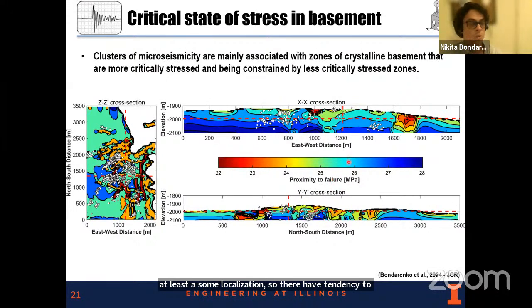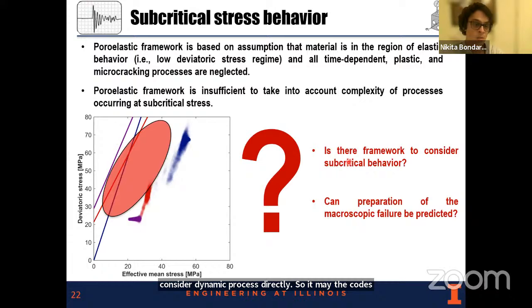At the same time, it should be noted that to perform computations faster, we used a quasi-static approach. This means we use damping for dynamics, so we don't consider the dynamic process directly. It makes the codes faster, but we don't consider dynamic rupturing directly. This is the main limitation if we look at this slide.